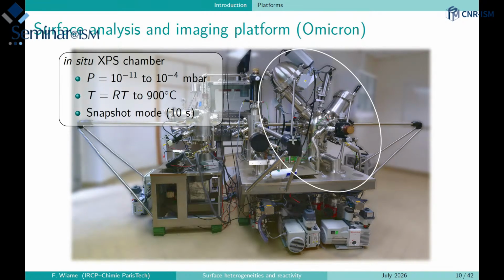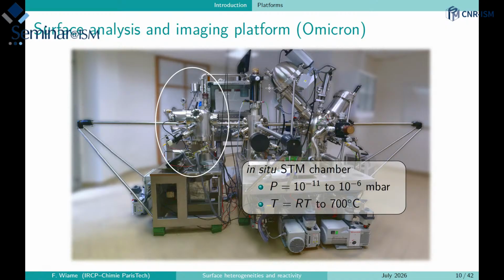We have the ability to work with snapshot mode, which is in fact recording the 128 parallel channels at the same time. So we can do one spectrum at one shot with 128 points. And if we want to have good statistics, we can record for generally about 10 seconds, and we can follow while we are exposing to the reactive gas, for example. While we are exposing, we can follow the reaction at the surface. I will show you some examples of this.